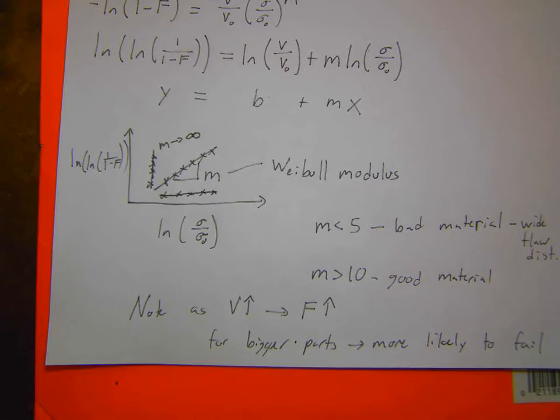So now if I change my Weibull modulus, change my failure strength. This is silicon nitride. I don't know if you can see exactly what those slider values are, but this is now a Weibull modulus of 10 or 11, and that's giving me a reasonably good fit, and a critical stress of 984. So almost a gigapascal for silicon nitride. But you can see some of these parts will fail at stresses of 700 MPa, and some of them will fail at stresses over a gigapascal. And so this distribution of flaws is what we're looking for in these brittle materials to figure out how likely failure is going to be.